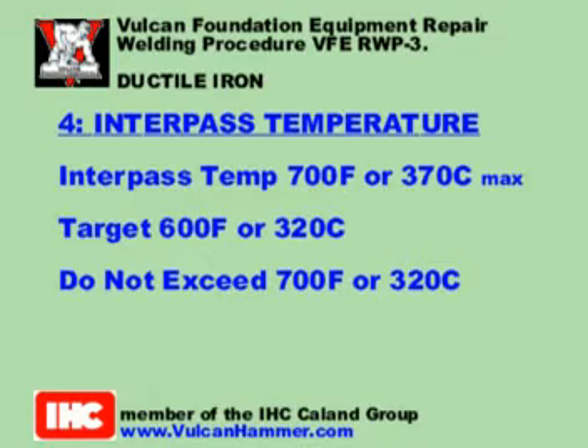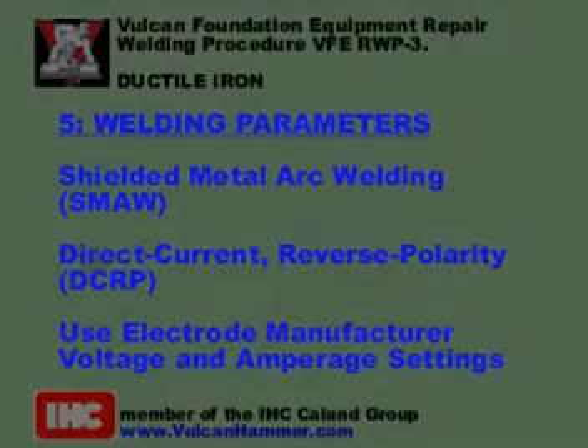Section 4. Interpass Temperature. The interpass temperature is 700 Fahrenheit or 370 Celsius maximum. When practical 600 Fahrenheit or 320 Celsius should be used, but in no case exceed 700 Fahrenheit or 370 Celsius.